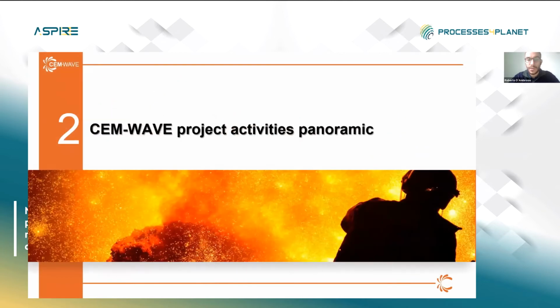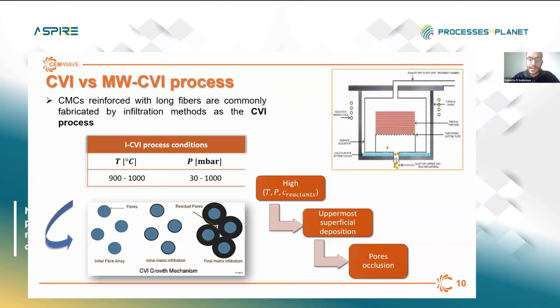So I will start now by going more in detail into the microwave CVI technology. Let's start by saying that commonly CMCs are fabricated by infiltration methods. Among those techniques, the chemical vapor infiltration, or CVI, is one of the most preferred, since it allows to obtain the highest quality matrix in terms of resulting thermomechanical properties. Specifically in this process, a gaseous ceramic precursor infiltrates a porous fiber structure and reacts at high temperature on the fiber surface, depositing a ceramic layer.